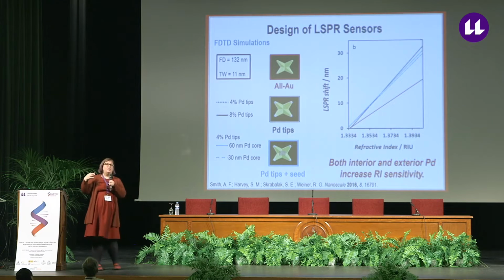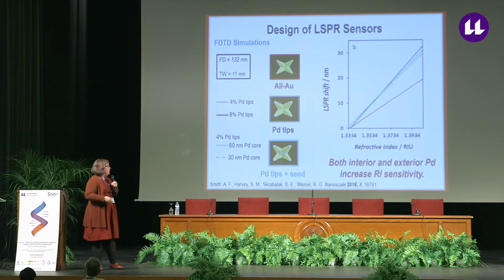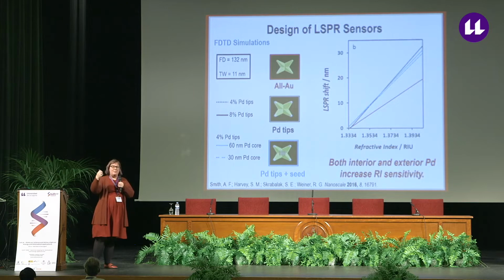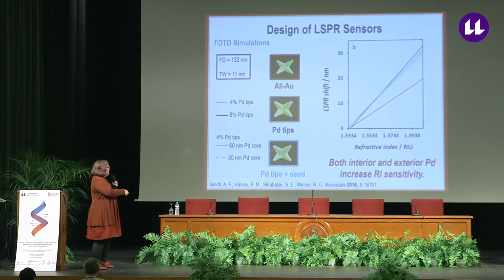So you'll notice that this is a pretty dramatic simplification of the actual compositional distribution. It's quite challenging to get accurate 3D distribution of the alloy, the gradient alloy in these nanocrystals, but we were thinking that palladium at the tips was probably the most important compositional feature. We also can build these branched nanocrystals from palladium seeds. So we put a palladium seed with palladium tips with the gold branches.